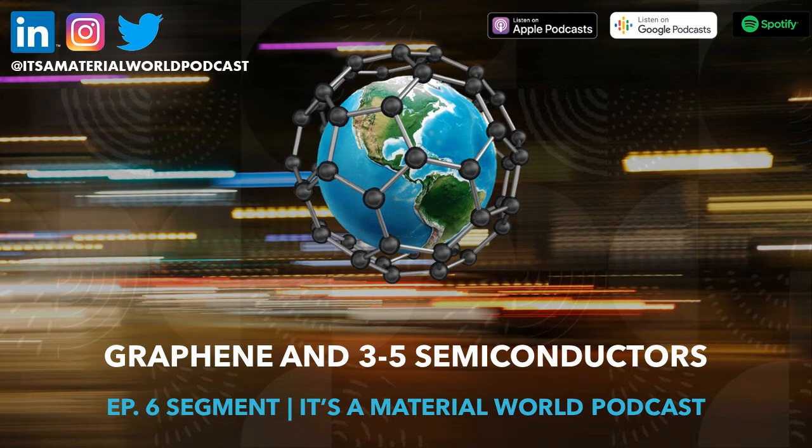The CTE, or coefficient of thermal expansion, of graphene and copper are very similar. And so for packaging applications, where you need zero stress between an interconnection, if you have a graphene-like material that can act as another substrate on the other end, the CTE mismatch is less, and it's called zero stress packaging. And that can be used as heat spreaders in packaging. So it has a lot of applications.